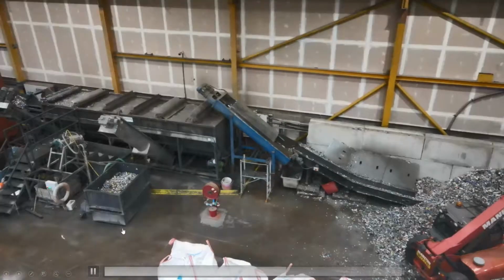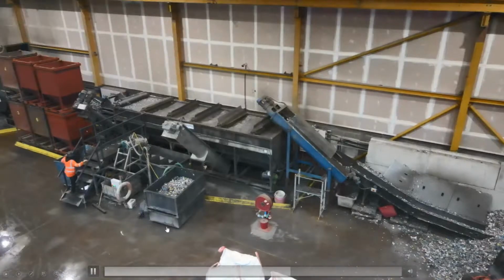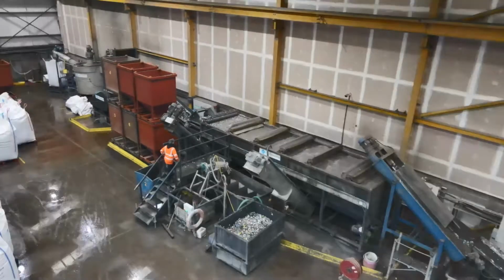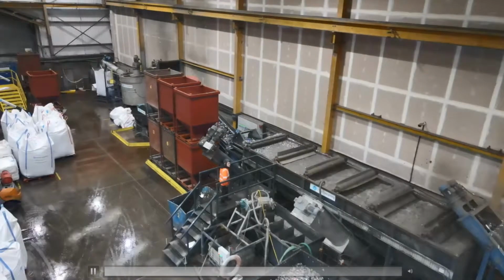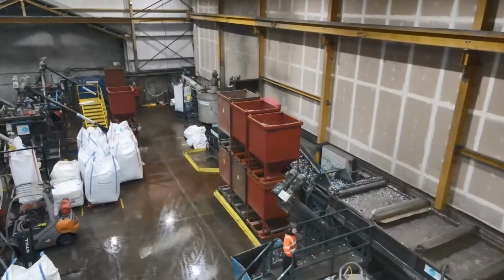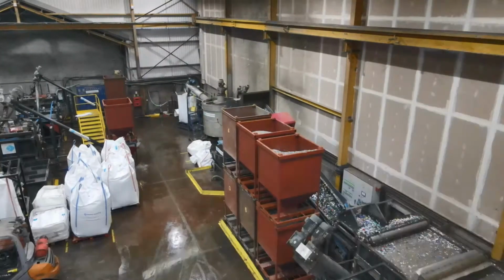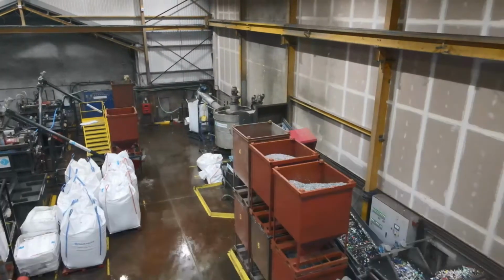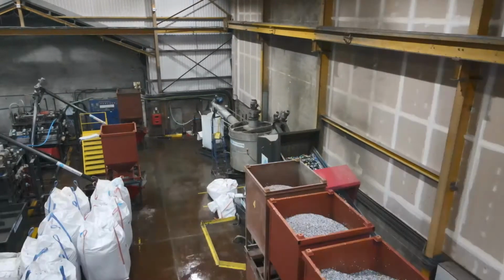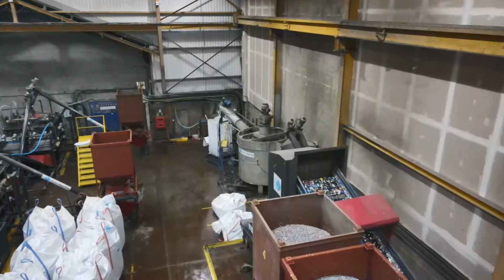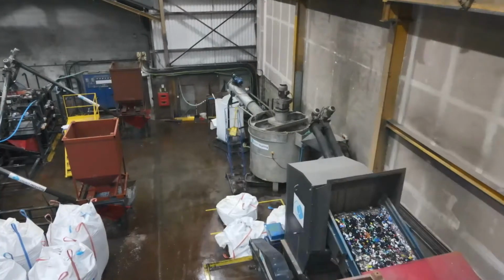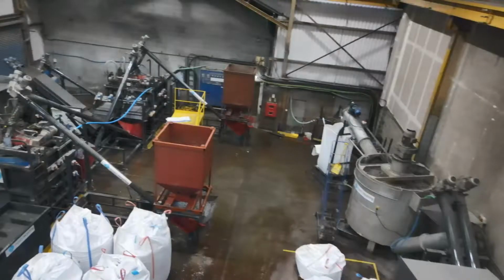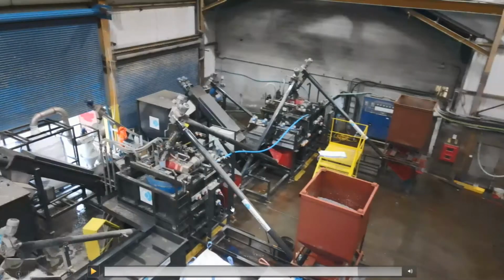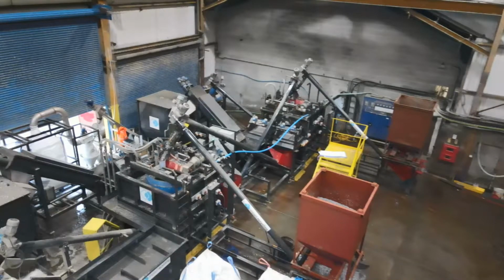From there, we wash the plastic and put it into a density separation tank. We're able to recover two sinking fractions there, one which is ABS and high impact polystyrene rich, the other that is PVC rich. This allows us to further recycle our non-target plastic components that exist in our feedstock. We put it through a very mild caustic wash before feeding it into our patented BOSS system, which we're looking at here. One BOSS has been optimized for delivering pure polypropylene, the other for pure polyethylene.